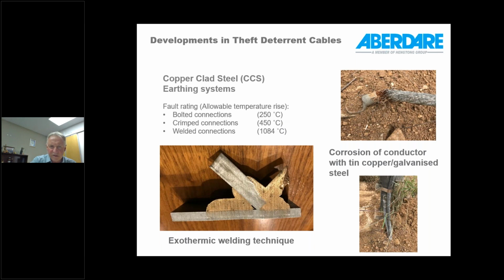So one would need to consider this when applying these conductors, that if such an earth conductor is right next to another cable, like in this picture for instance, having this conductor go up to 1,000 degrees is not going to be very good for the cable that it's installed next to. And of course, as we spoke earlier, bimetallic corrosion is a problem with these type of conductors as well, when you're talking about bimetallics. But for copper-clad steel, corrosion is not an issue.